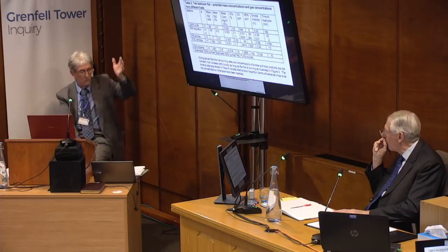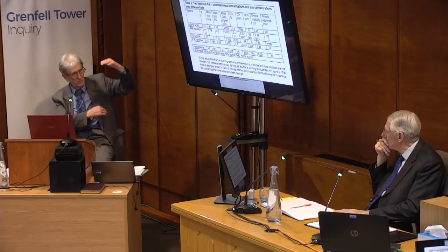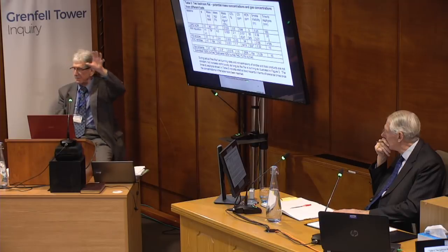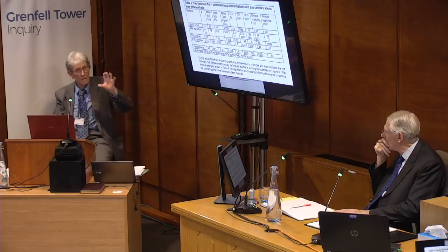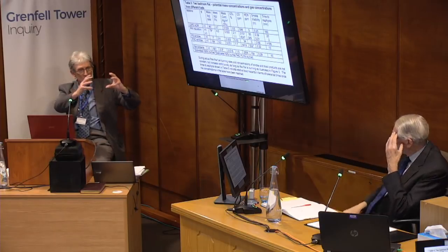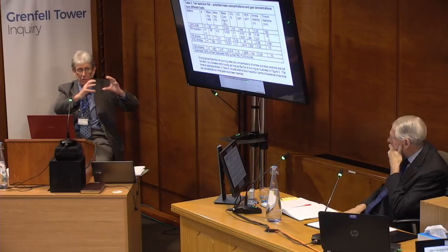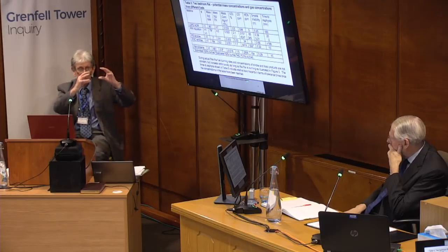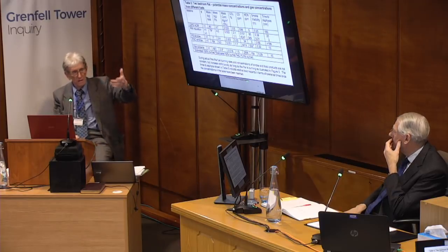And in fact, we took some specimens of this and sawed through them. If you look at a cross-section of one of these charred pieces, it looks a bit like a loaf of bread that's been burnt in the oven, so that you've got this kind of charred exterior of a certain thickness, which is the way it's designed to happen. And then behind that, you've got some creamy-looking, apparently intact PIR that's not been decomposed at all. But the bit that's charred, although there is significant carbon still left, which is the char, will have lost a considerable part of its mass.